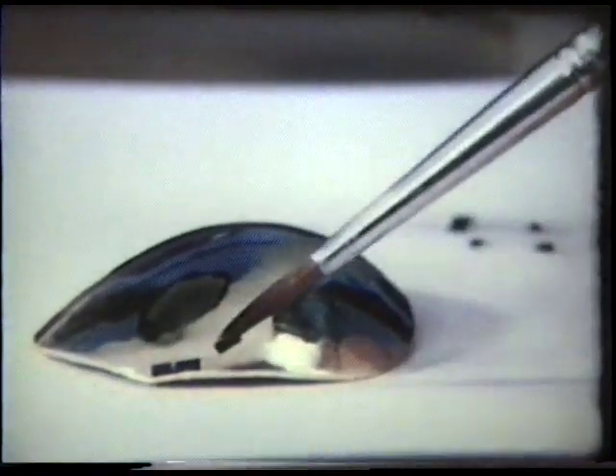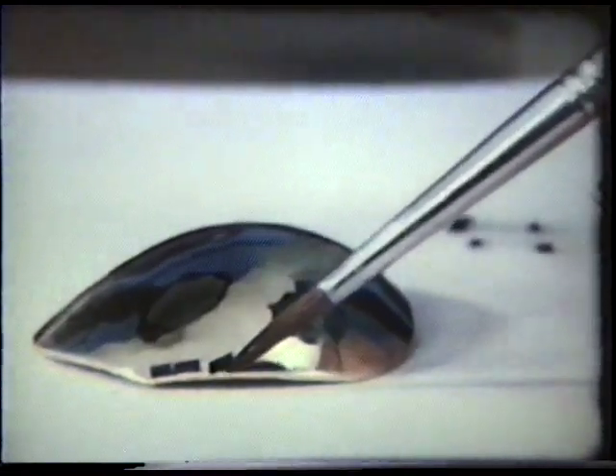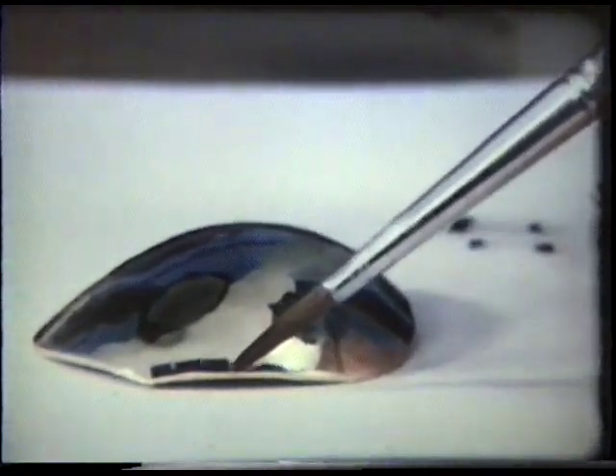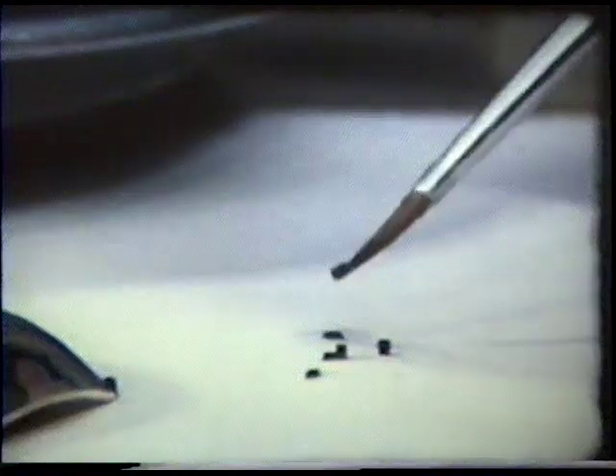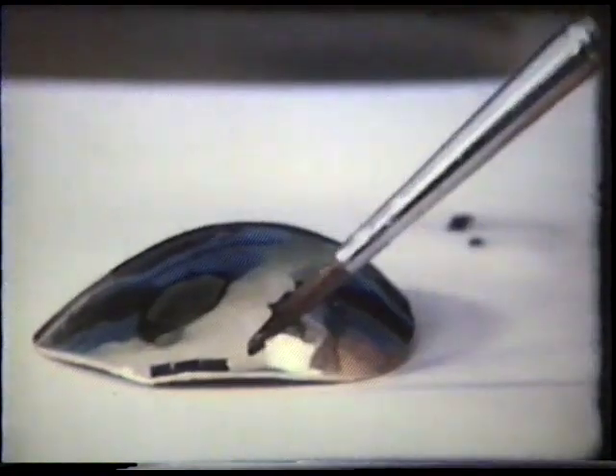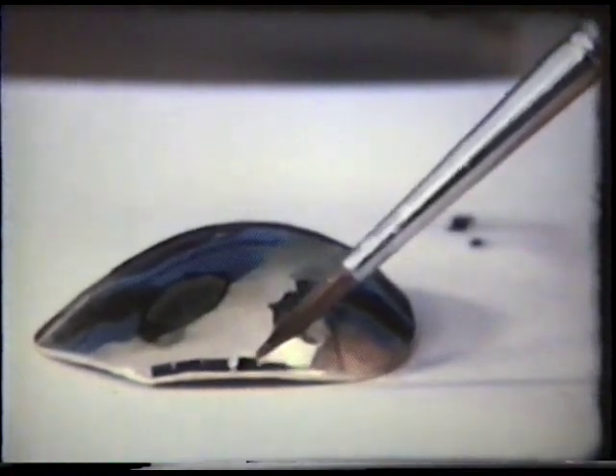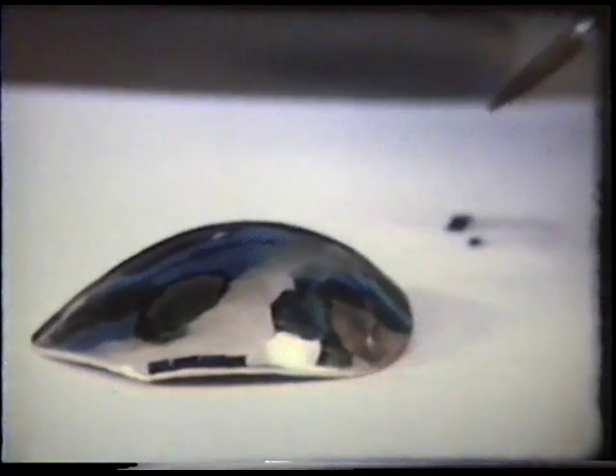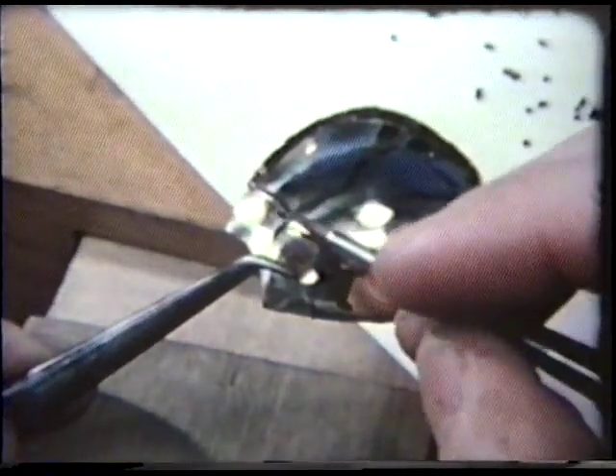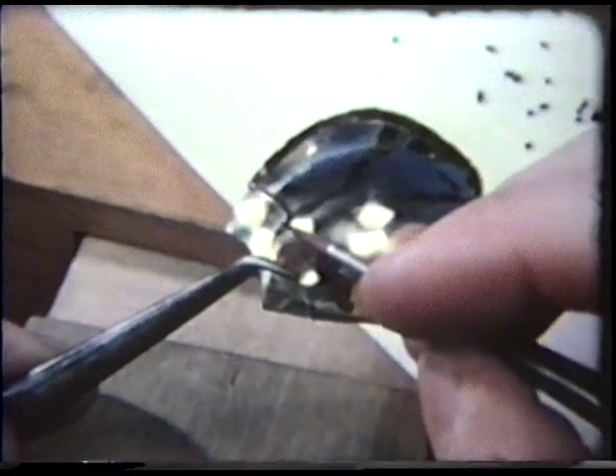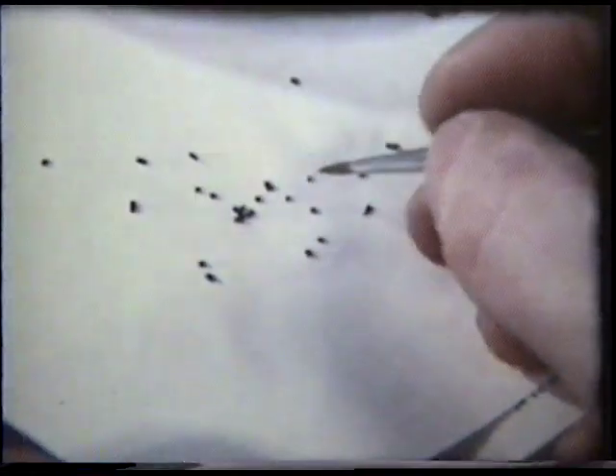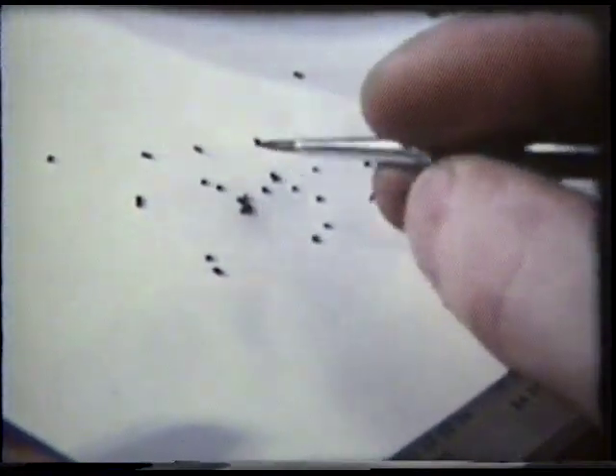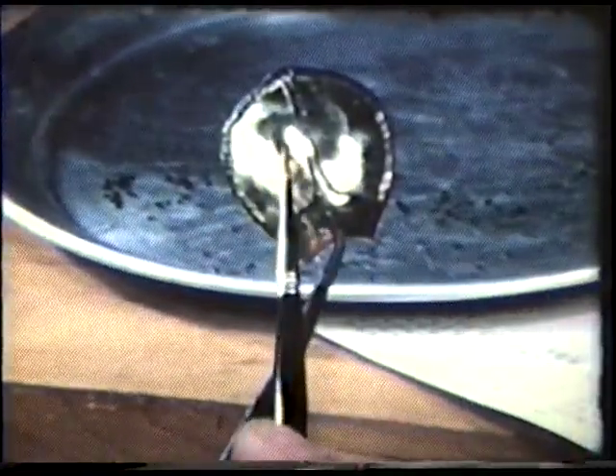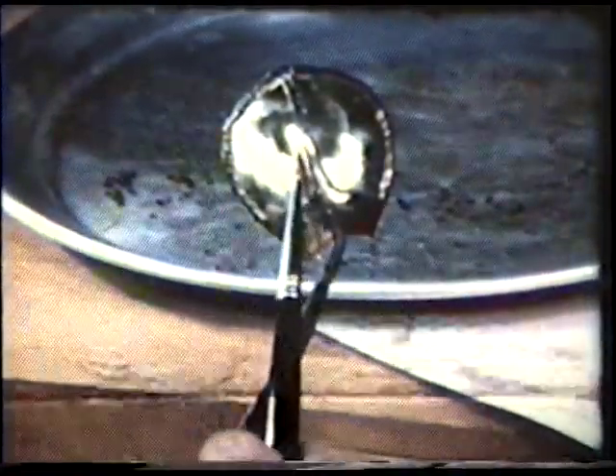Each piece is picked up and positioned with a small brush moistened with a solution of gum tragacanth, a vegetable glue. The rectangles are placed end to end to form lines that define the large areas of the back. Standing on edge, these rectangles develop a wall about 1/16 of an inch in height. Traditionally, these walls were made by bending strips of gold wire to fit the form and fusing them in place. The fragmented line achieved by the rectangles produces a line that is less mechanical in feeling.